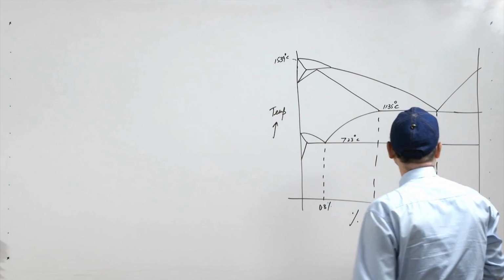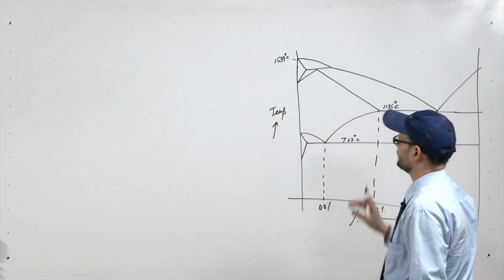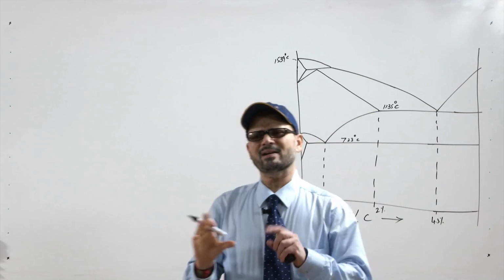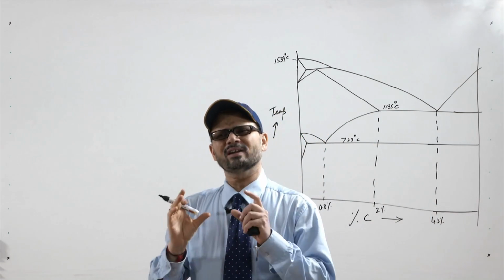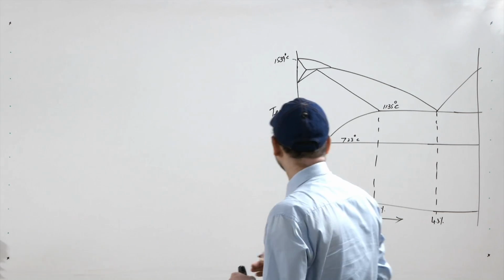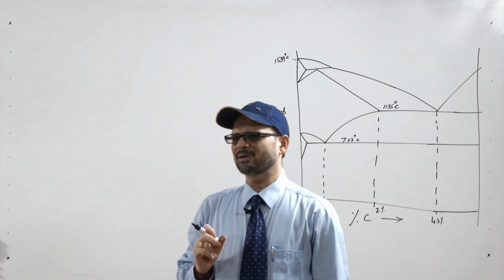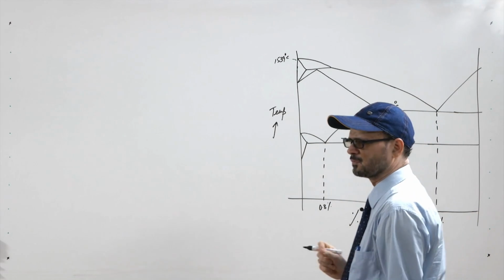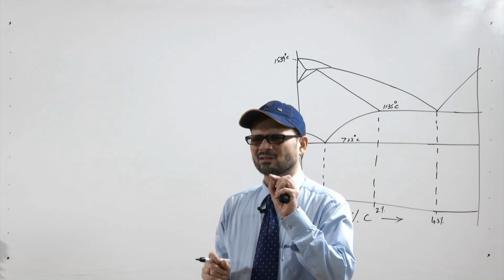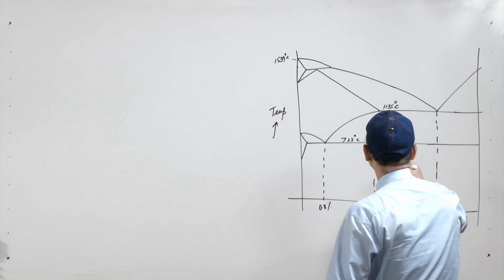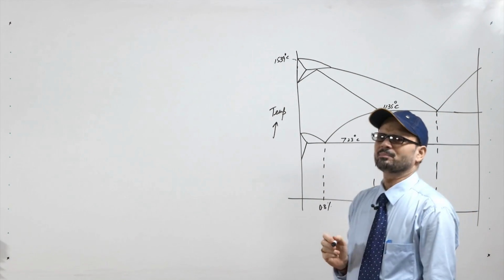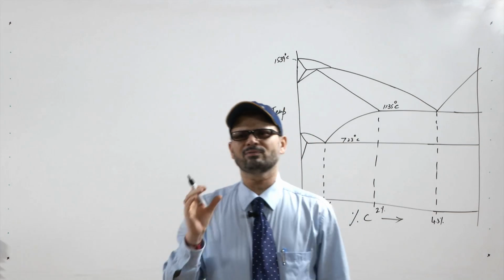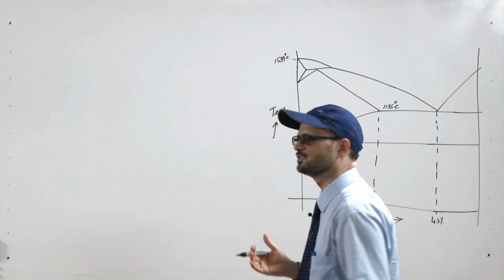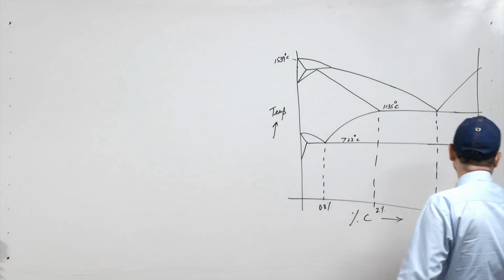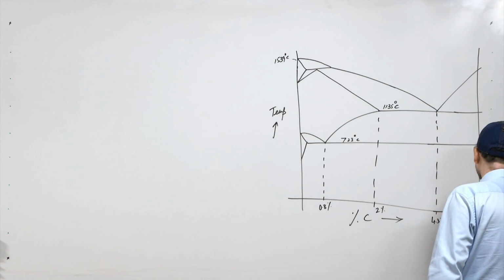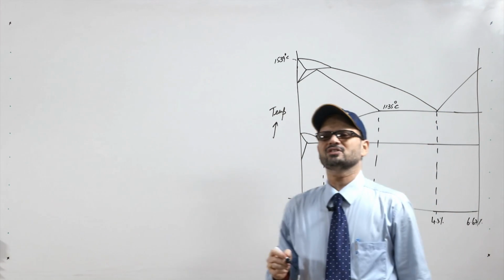Apart from that, in the case of cast iron, apart from iron and carbon, one of the chief alloying elements which plays an important role is silicon. Silicon is a graphitizer. The carbon in steel up to this point is normally present in combined form with iron as Fe3C, because this 6.67% is Fe3C, the intermetallic compound cementite.